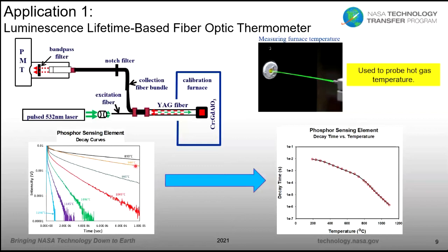For some rather modest increases in temperature, we get a significant change in slope. Again, remember, the intensity is plotted on a log scale. Okay, so then at the different furnace temperatures, we can plot the decay time versus temperature, get an excellent calibration curve fit by the same equation I showed before. A very good signal to noise.